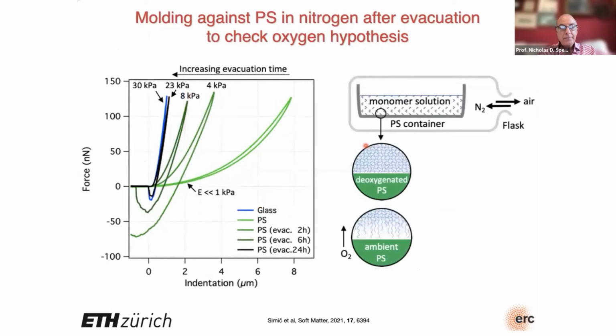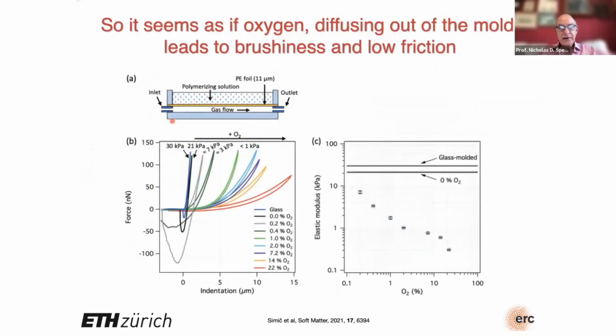And then we also did experiments just to confirm it. We deoxygenated polystyrene and then backflushed with nitrogen. We found that the longer we deoxygenated it, or the more efficiently we deoxygenated it, the more like glass the polystyrene behaves. So it really seems to be the oxygen diffusing out of the polymers that is leading to this effect. And this leads to a way in which you can actually control the friction on the surface of the hydrogel. You can have a gas flow, for example, underneath and change the amount of oxygen in there.